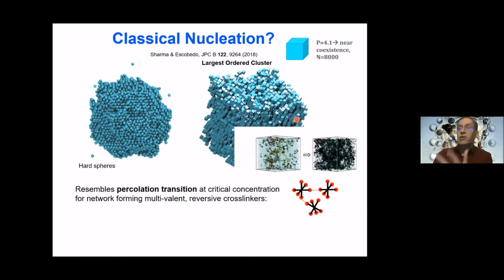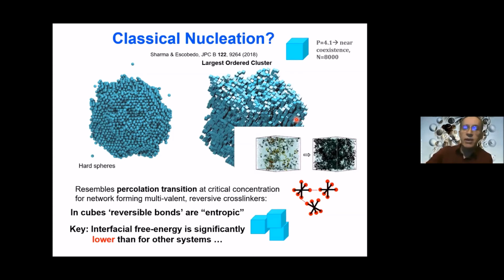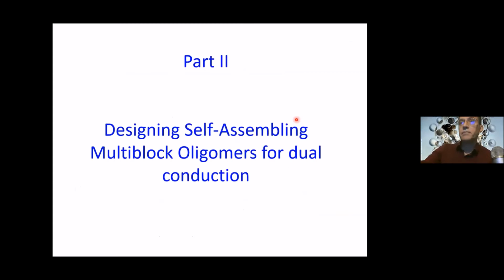So we're still trying to understand this, but it resembles a lot a percolation transition that's sometimes seen in some polymer systems that form networks with multivalent cross-linkers. In our case, we have perhaps these weak reversible bonds because they're entropic, but something that we have found recently that we think is going to be key to explain this behavior is the fact that the interfacial free energy between the solid and the liquid is very, very small compared to that of other systems. And we're still trying to understand why this is, but I think that's going to be a very interesting story once it's completed. So I think I'm ready to move to part 2, unless there is maybe a quick question on part 1.